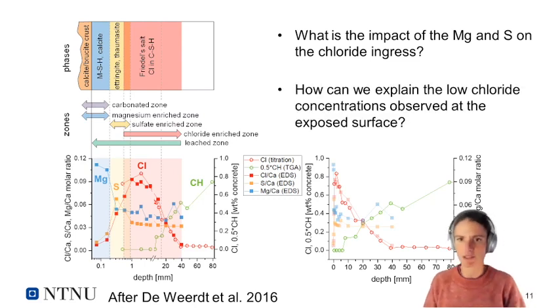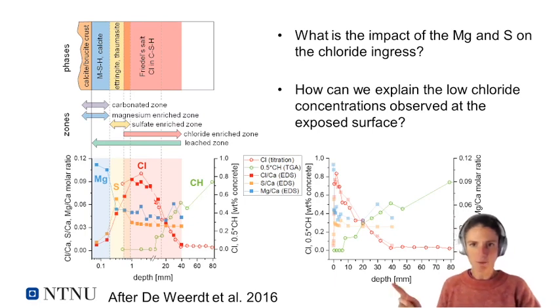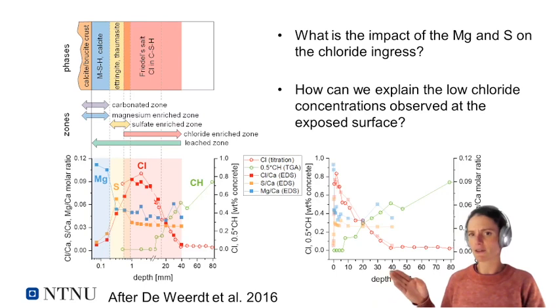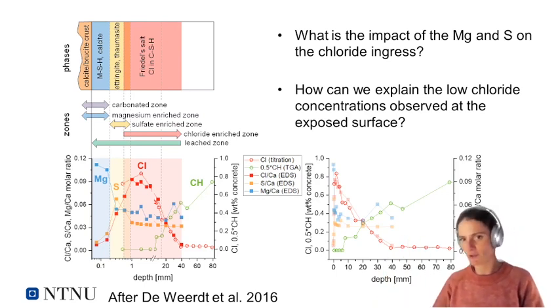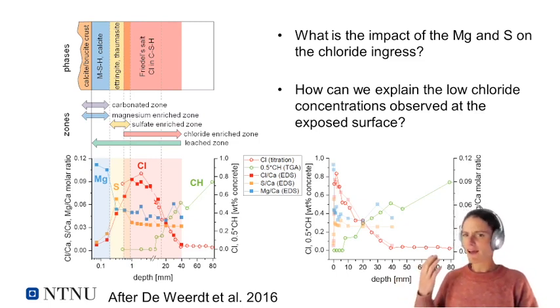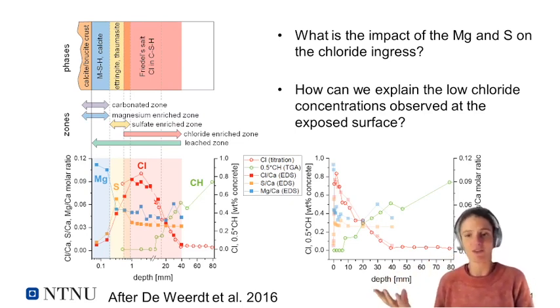And the second question is that I want to draw your attention once more back to the graph on the left here, and to the blue zone where you have the magnesium enrichment. There, the chloride levels are really low. So at the surface, chloride levels in our concrete are low. We always learn that chlorides move from the higher concentration to the lower. So the surface concentration should be the potential for chloride ingress. But what we're seeing here is that at the surface, the chloride concentrations are lower than slightly deeper in. How does that match with chloride diffusion? What does that actually indicate? So I wanted to understand this better. Why are the chlorides at the surface actually rather low?